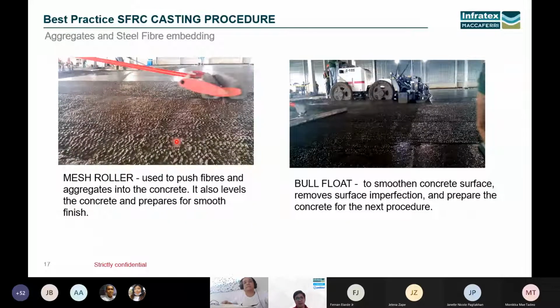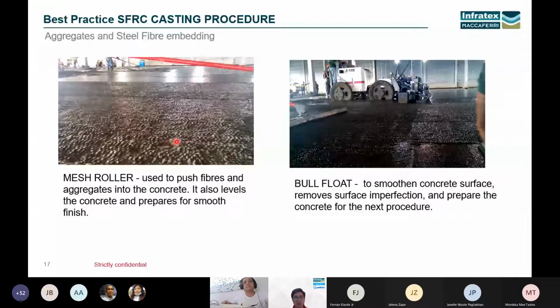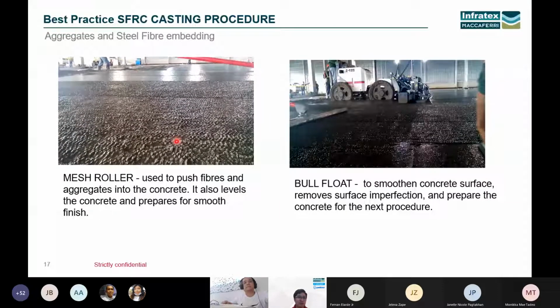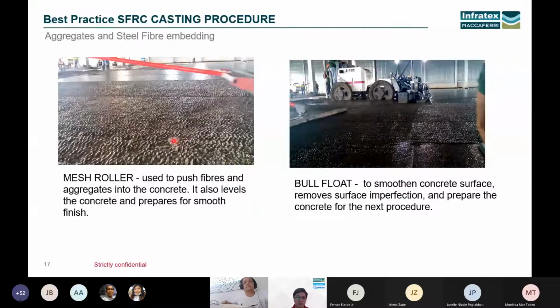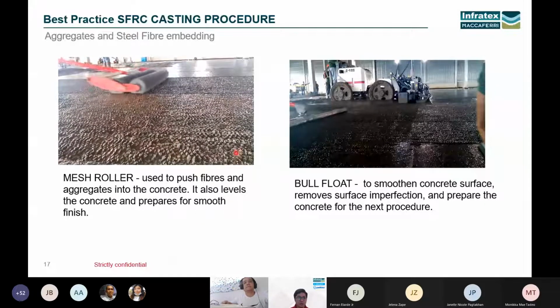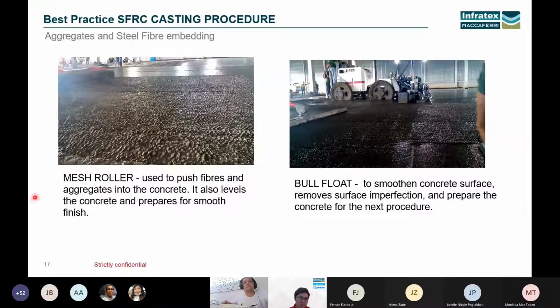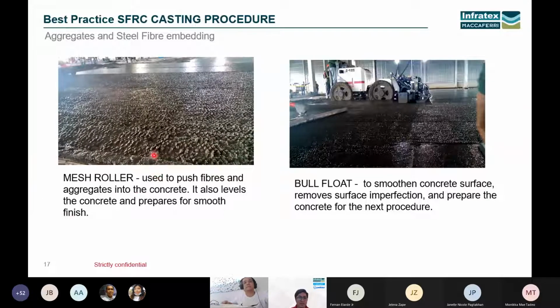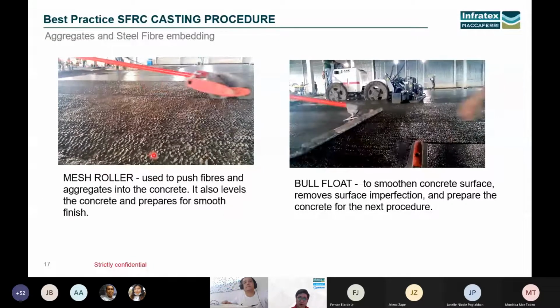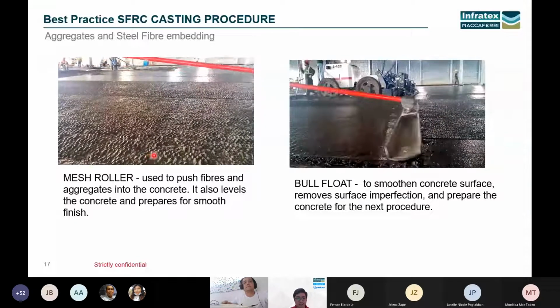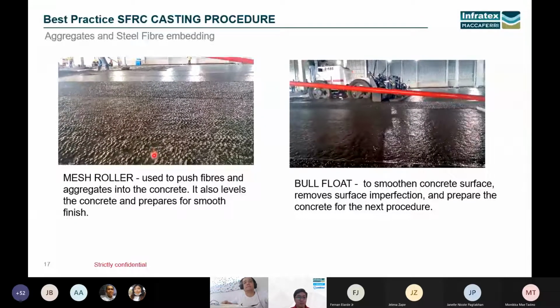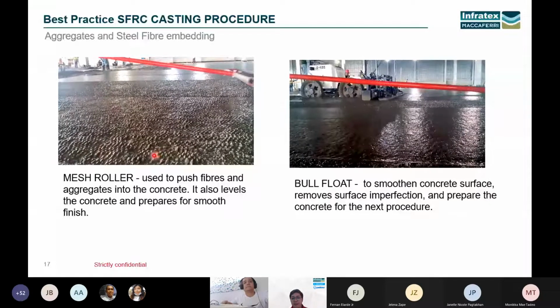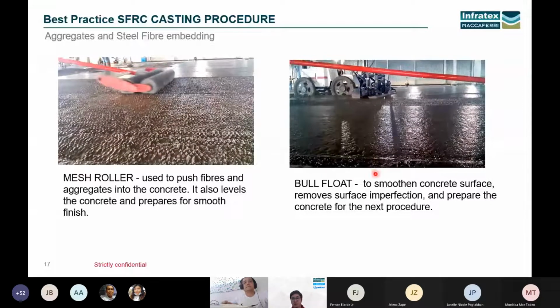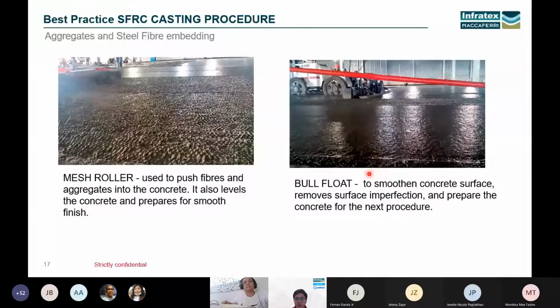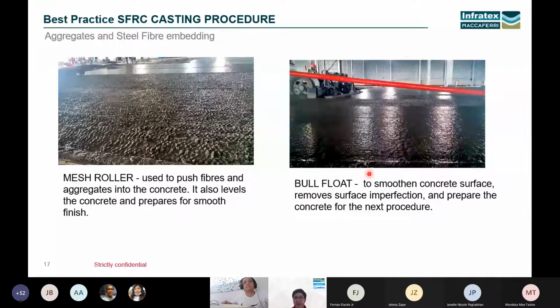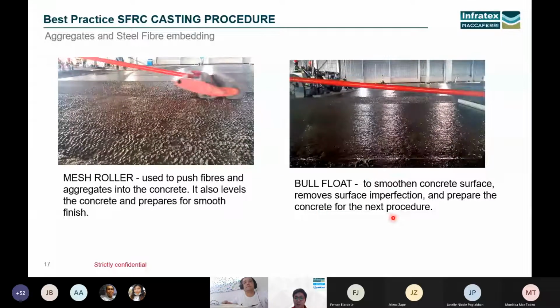After that, the next step is to make sure that there's no sticking out or floating aggregates and steel fibers at the surface of the concrete. The best way to avoid that is by using a mesh roller. The mesh roller basically pushes down or depresses the aggregates and steel fibers into the concrete, and it prepares it for the smooth finish. Then the next step would be bull floating. Bull floating is to further smoothen the concrete surface and remove the surface imperfections.